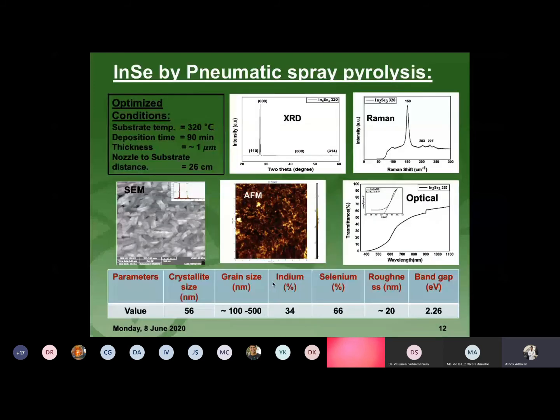For the synthesis of the absorber layer, the optimized condition is 320 degrees Celsius with a deposition time of 90 minutes. With this time and temperature, we get 1 micrometer of thickness.